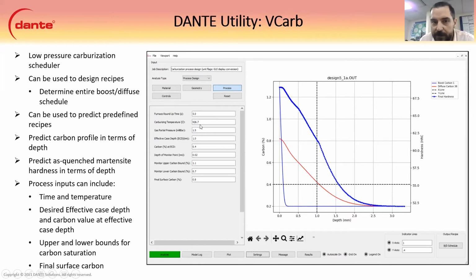We have the carburizing temperature, so what temperature you're carburizing at, and partial pressure in the chamber. The important ones here are the effective case depth of 1 millimeter, and then the carbon at that level, which is 0.4 carbon. And then we have a monitor point, which helps us control the boost and diffuse, how long it boosts for and how long it diffuses for. And then those help put in the upper and lower bounds. So it'll boost up to that 1.1 for this one, and then it'll diffuse down to 0.7. And then the final surface carbon, like what you want on the surface.